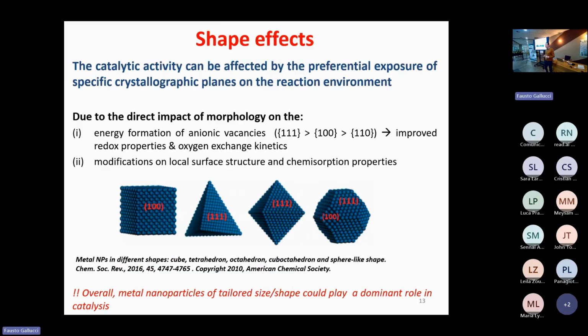Besides the significant modifications that can be achieved by decreasing the size down to nanoscale, another adjusting parameter is the shape, the so-called facet-dependent reactivity. In particular, the catalytic activity can be notably affected by the preferential exposure of specific, as you can see here, crystallographic planes to the reaction environment. And this is due to the direct impact of morphology on the formation energy of anionic vacancies, as well as on the modifications of local surface structure and chemisorption properties. Overall, we can say that metal nanoparticles of tailored size and shape could play a dominant role in catalysis.